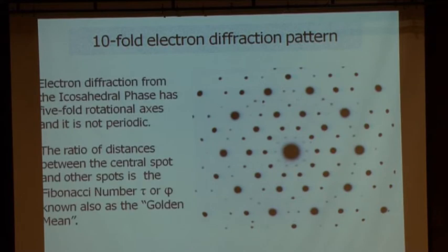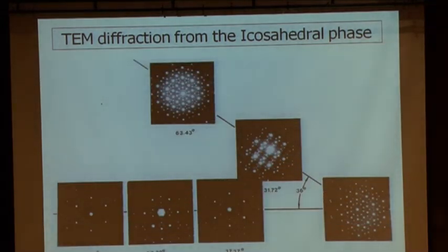Okay, so let's go further. The 5-fold or 10-fold rotational symmetry, by the way, as you have seen, there was a 10-fold rotational symmetry. It turns out, and I could not know from that experiment, that it's not really 10-fold, but rather 5-fold. It required a different experiment, which I did a few days later, to see that it's really 5-fold rotational symmetry, but it doesn't matter now. So if you take the crystal, this is the 5-fold, and then there is 2-fold and 5-fold again, and so on and so forth, 3-fold, 2-fold.